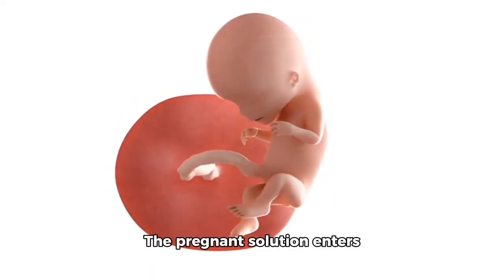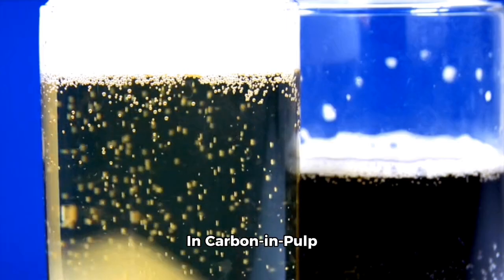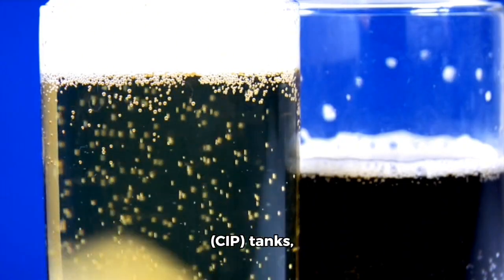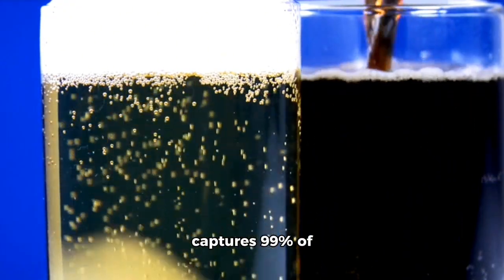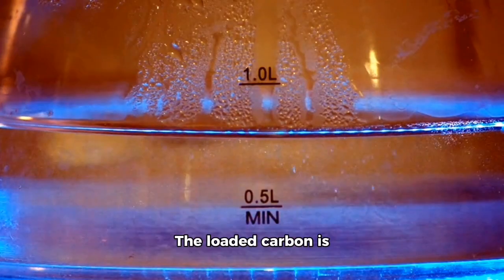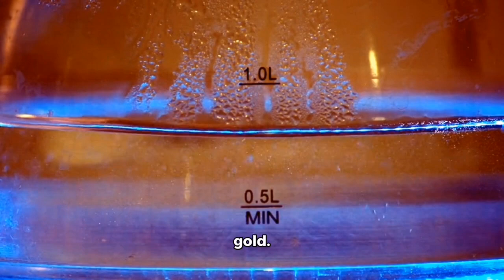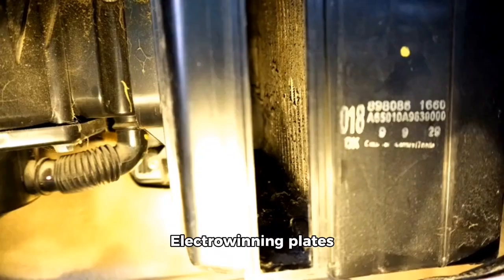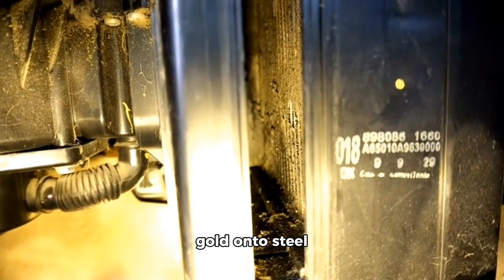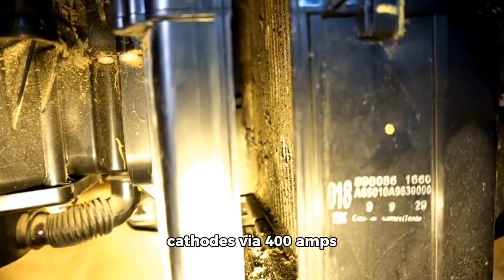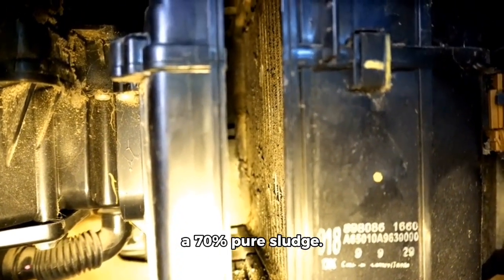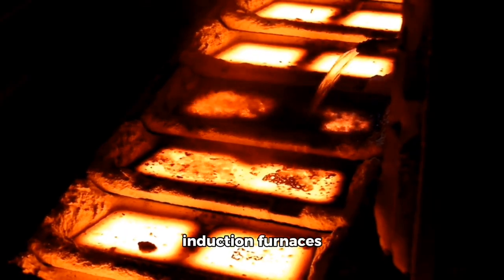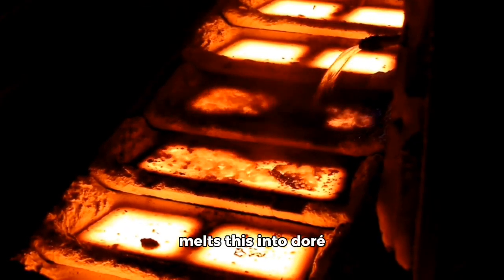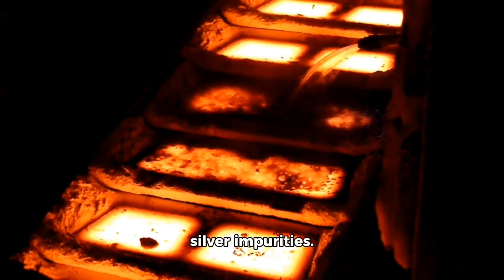The pregnant solution enters adsorption and elution. In carbon-in-pulp CIP tanks, activated carbon captures 99% of dissolved gold. The loaded carbon is stripped in elution columns at 140 degrees Celsius and 4 atmospheres, using a caustic soda solution to release gold. Electrowinning plates gold onto steel cathodes via 400 amps of current, producing a 70% pure sludge. Smelting in induction furnaces melts this into doré bars, 90% gold with silver impurities.